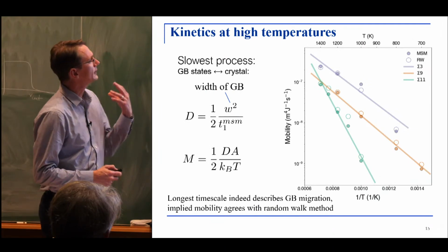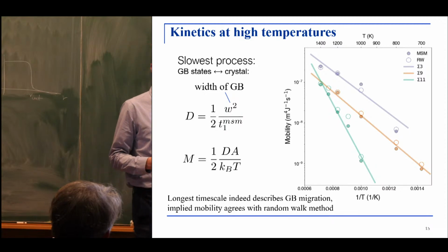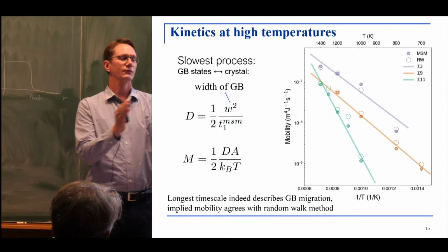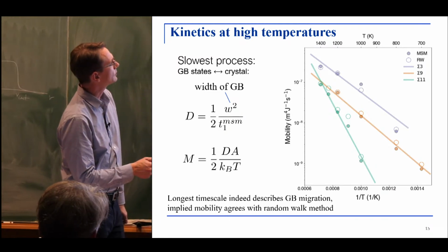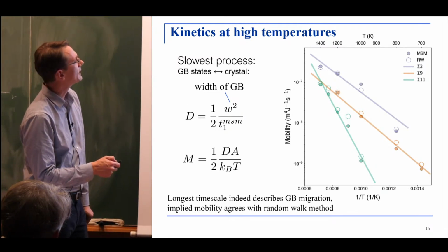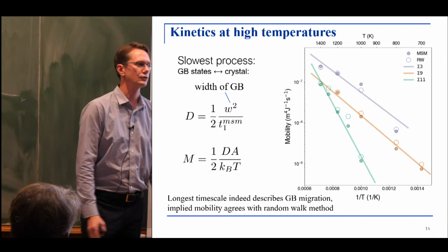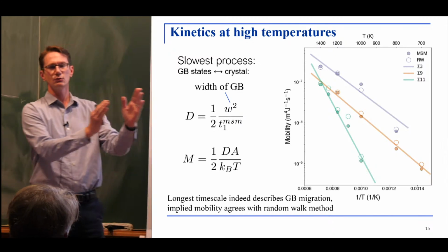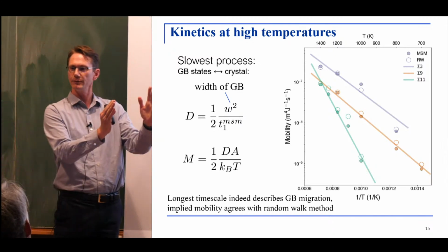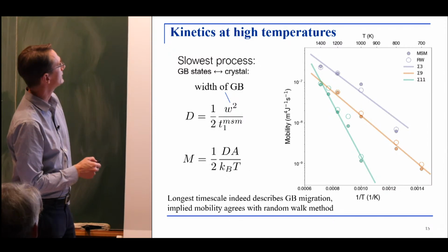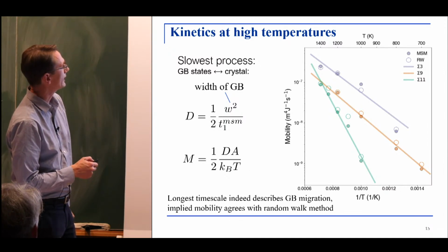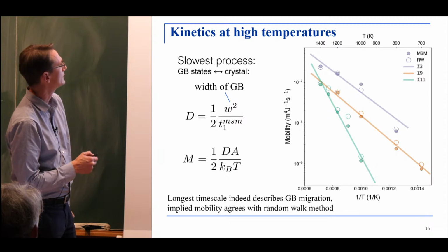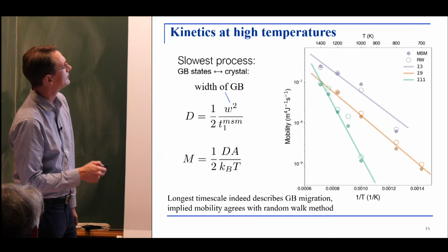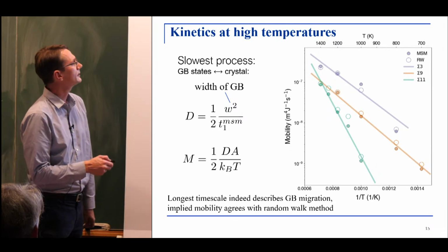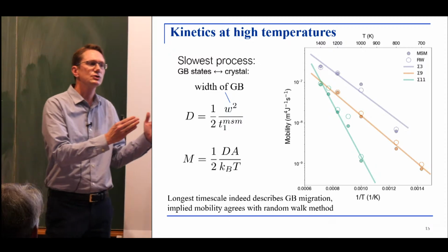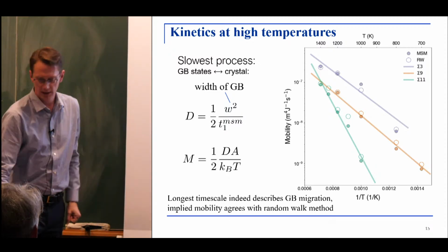This graph now shows you that the slowest timescale of the model indeed describes the overall translational mobility of the boundary. The open symbols is the mobility obtained from the conventional method that I described before. So you do a brute force molecular simulation, and you actually watch the boundary move, and you infer the mobility from this. And the filled symbols are the mobility that would be inferred from our Markov state model. Here one has to, as an input, define the width of the boundary. That can be done. And then you can see that these 3 boundaries more or less agree in terms of their mobility. So indeed, we can capture the macroscopic mobility of this system using this method.